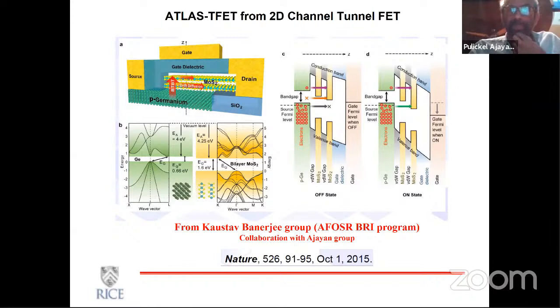Typically in electronics, when you go to very small scales, the gate voltage or the turn-on voltage doesn't really scale with the scaling down of the device structures. But it is shown that if you can find the right kind of architecture and right kind of devices, like a band-to-band tunneling device in this case, then you can avoid some of these problems and even break the thermodynamic barriers. So there is that part of the 2D material systems where people are looking at new architectures for devices and so on.